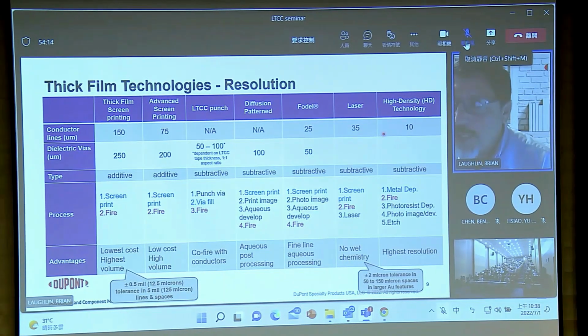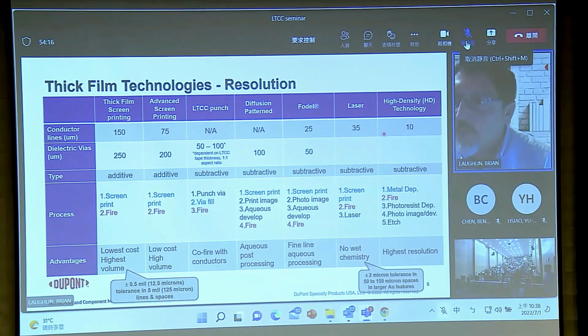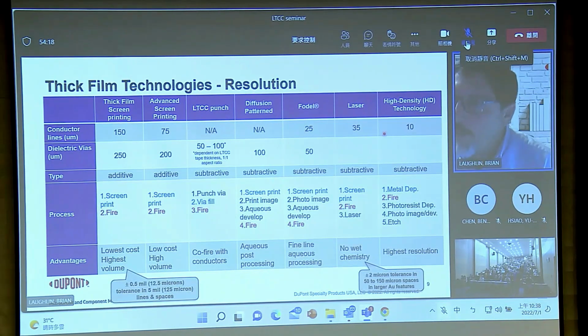And then if you really needed the most high density circuits, you can still go to a photolithography method. So you would do your screen printing or whatever metal deposition, do some firing step, and then you would use photoresist, probably like a dry photoresist like Riston, do photo image develop, and then use a wet etch chemistry to etch back what you don't want.